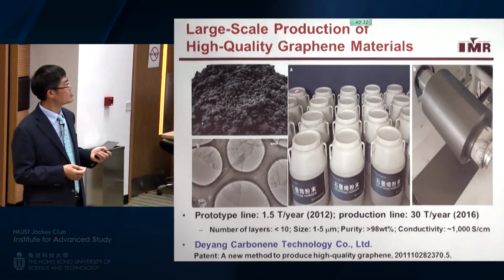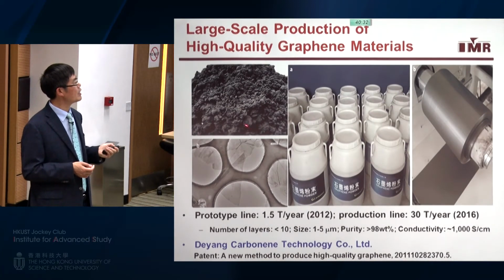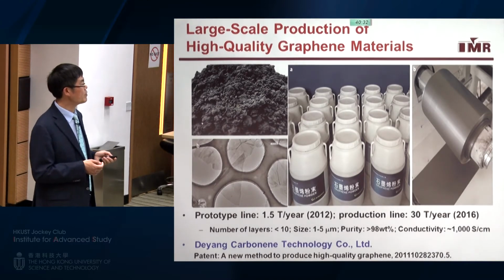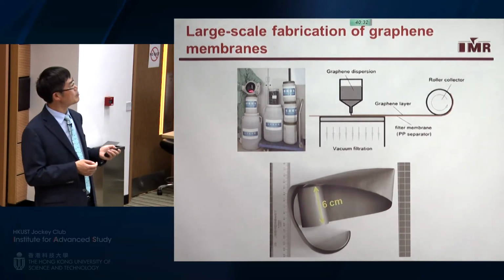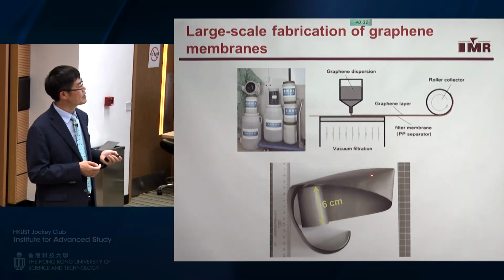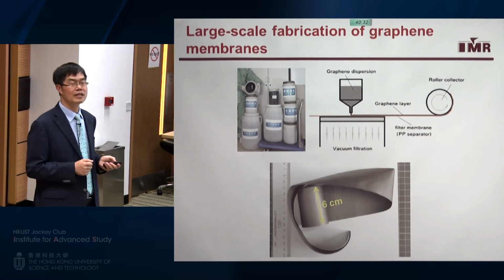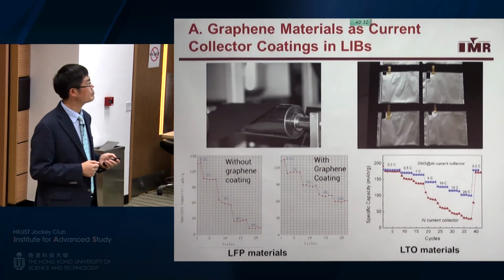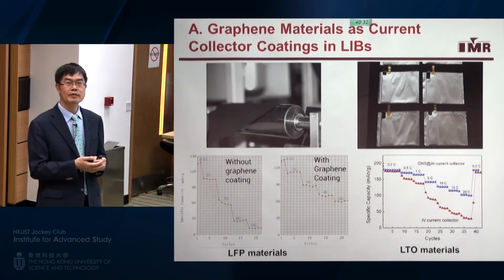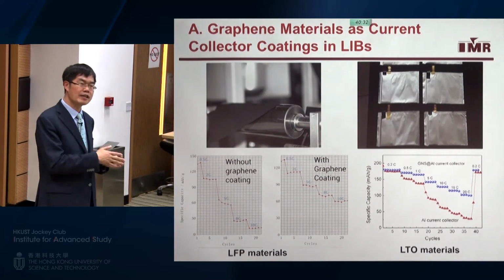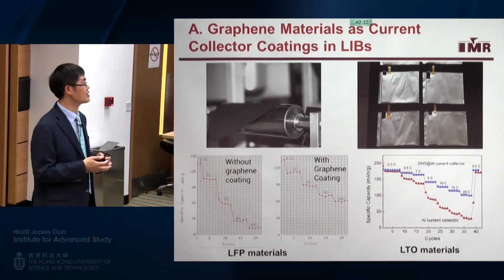So here I show you some large scale produced graphene powder and suspension, in cooperation with our company in Sichuan province. It's called Deyang Carbonene Technology. And this method is by intercalation exfoliation. With those materials, we can very easily make this membrane, and also quite easily make a three-dimensional material as well. So therefore, we can use it for some practical application and also for some research.